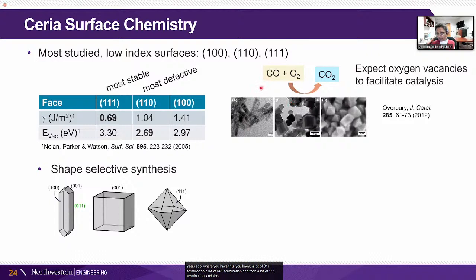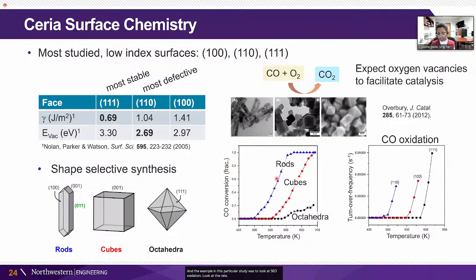And the example in this particular study was to look at CO oxidation, look at the rate of that. And what was observed was that indeed the rods with the lot of 110 termination were the most active, then the 100, with the intermediate concentration of oxygen vacancies, at least computationally expected, moved up in terms of activity. And then the lowest was the 111, which had nominally the lowest oxygen vacancy concentration. So this looked like an open shut case that the explanation was there.